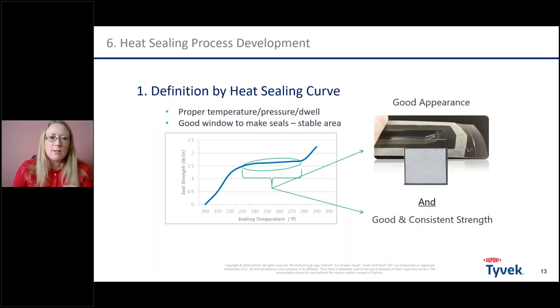So you can measure seal strength, for example, with ASTM F88 as the test method. And then you can analyze it together with your visual appearance, a visual control. You will, of course, also examine the seal quality. So you can find the area or the range where you have a good seal appearance and a consistent and good, appropriate seal strength.